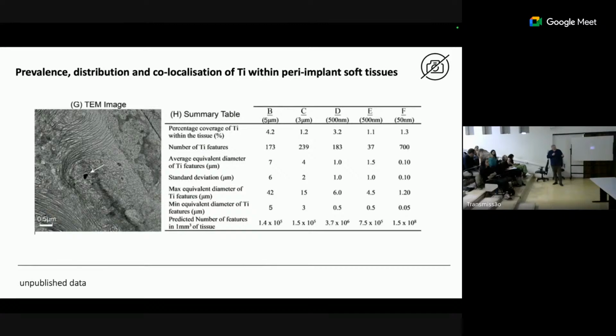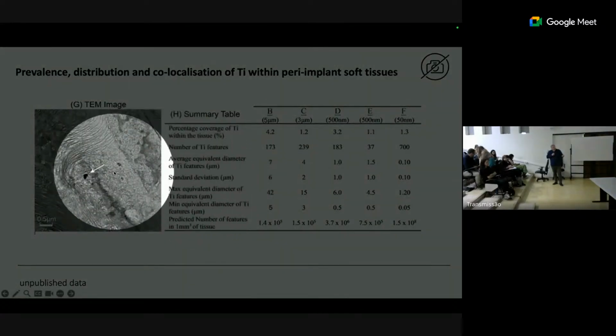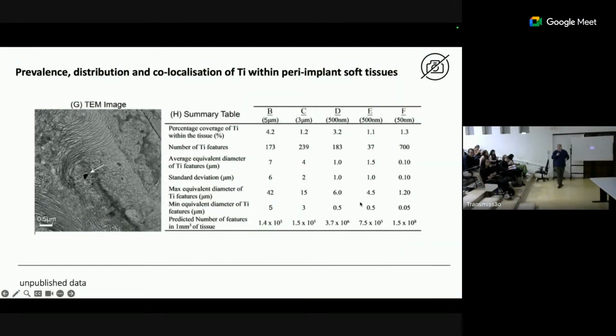I put a TEM up here to show sort of what an individual particle would look like. But what we found is that in different tissue sections, so this is in a millimeter cubed, you would have something like 1.5 times 10 to the 5, 3.7 times 10 to the 6. So we're talking approximating 4 million particles within a 1 millimeter cubed piece of tissue, which doesn't sound too good in terms of a biological response.